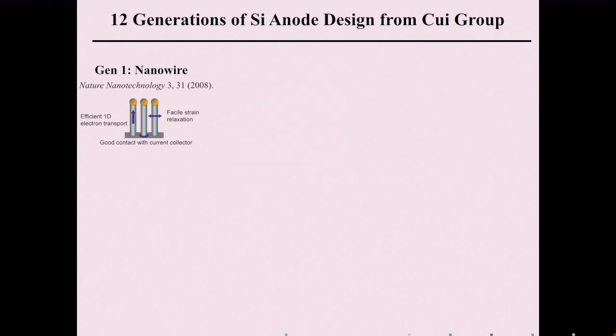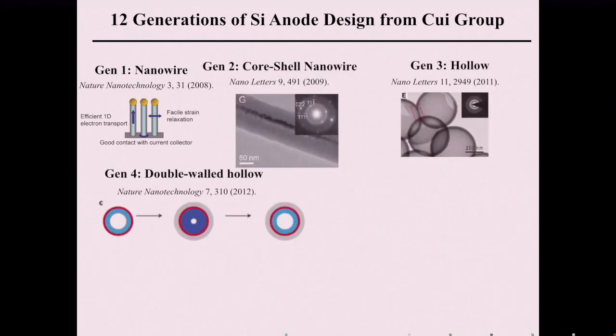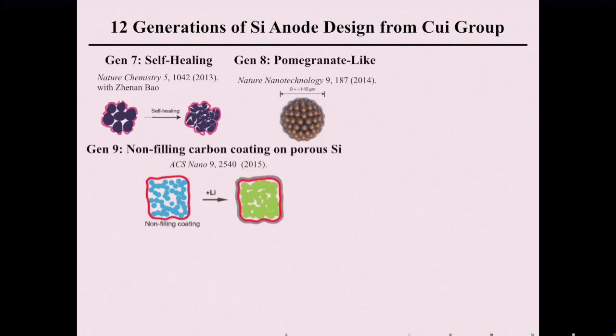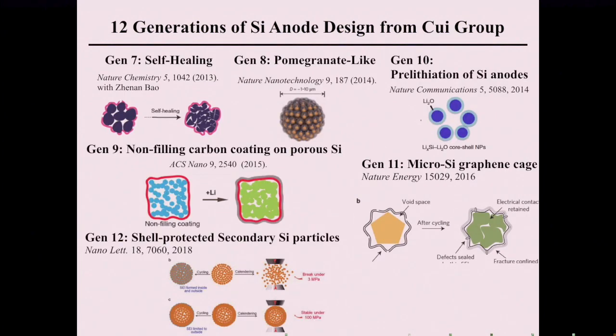This is the paper we published back in 2008 using silicon nanowires to take in a lot of lithium, 10 times more than graphite. And it has the breaking problem. It has many issues showing up. By using this nanotechnology design, we were able to overcome the breaking problem. So fast forward, we have been through 12 generational designs to solve instability of the interface issue and so on.